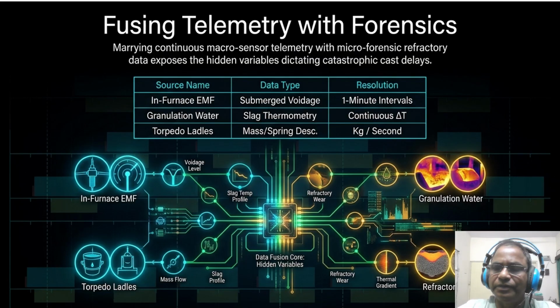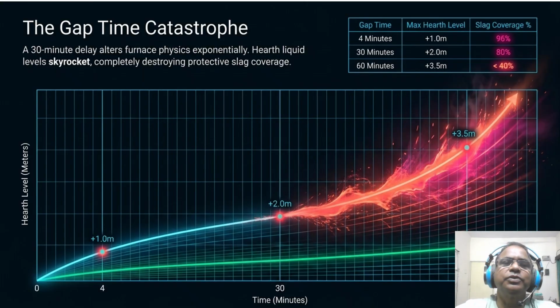So this slide features a striking exponential graph. The x-axis is time in minutes and the y-axis is the hearth level in meters. Look at the blue line. For the first few minutes, the rise is linear. But at the 30-minute mark, the curve turns red and skyrockets. Simultaneously, look at the table at the upper right. At 4 minutes, you have a 96% slag coverage protecting your hearth wall. By 60 minutes, that coverage dropped to less than 40%.